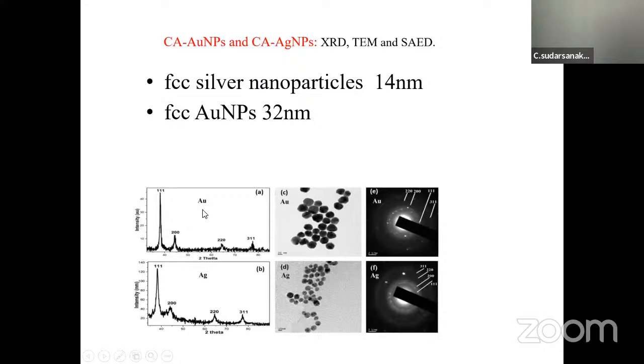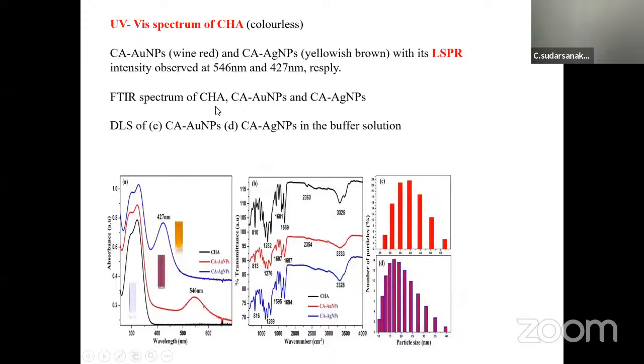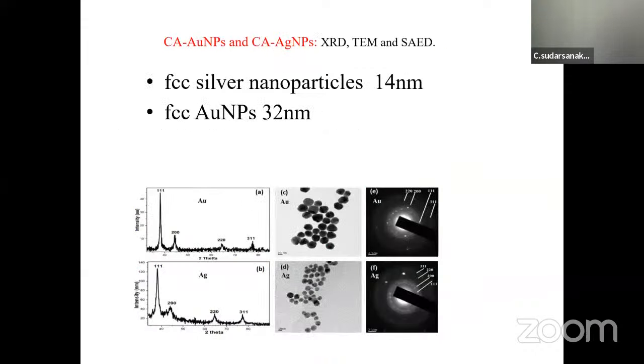This is the silver nanoparticle. This is the gold. The XRD pattern says both are FCC structures, and the shapes are spherical, not exactly spherical, dodecahedral. This is the SAED pattern. All these correspond to the structural information available in the literature. This is a pure characterization of that. Even UV characterization will tell you the same absorbance for gold and silver. The particle size and FTIR are all just to characterize whether the particle formed is silver or gold.